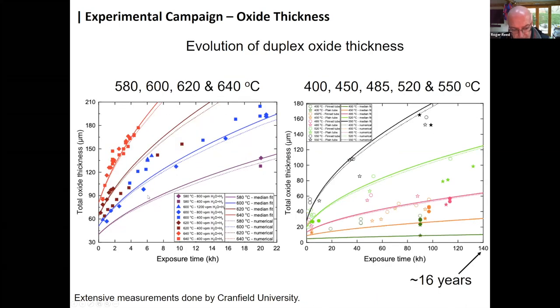I also would like to credit Cranfield University, because you can see from the evidence I presented so far that the attack is quite aggressive, so that once the attack starts to go, we need to know how much of the metal has been degraded and destroyed by the oxidation reaction. So I'd like to credit Cranfield University and also Loughborough University and Birmingham as well, who have made lots of measurements of the thickness of the oxide as a function of different geometries and temperatures and times and so forth, which has helped us with our modelling activity.